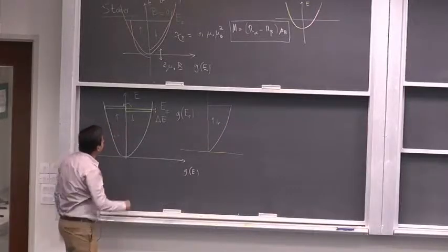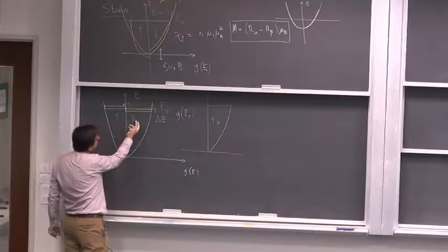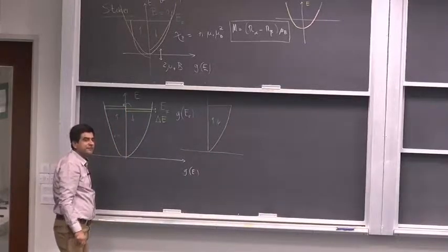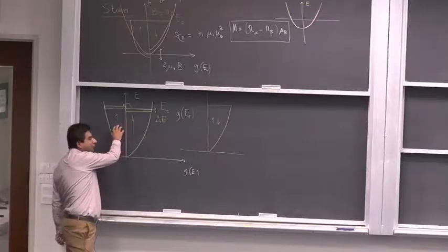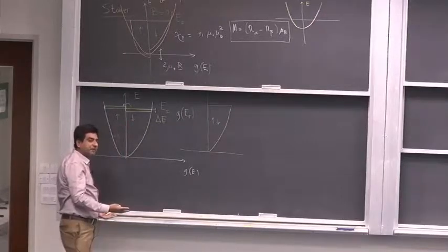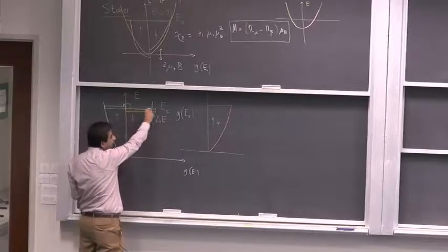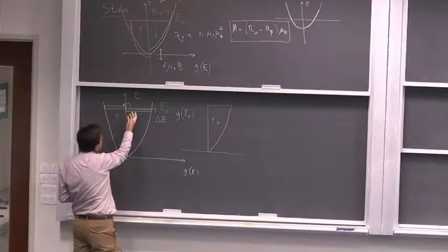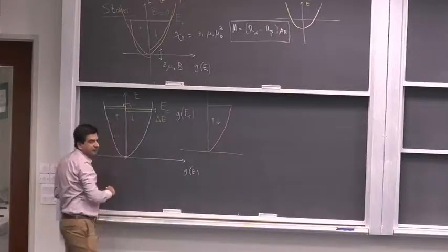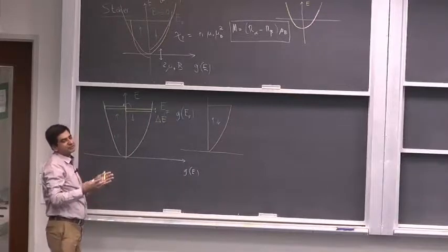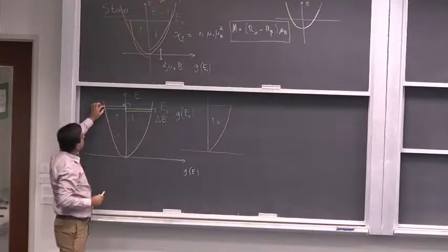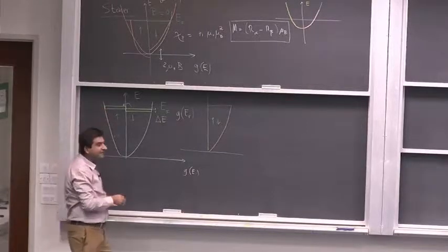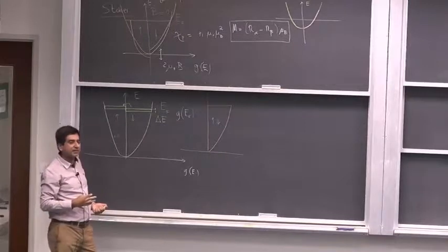Okay, so now what we're doing is we're flipping, reversing these spins and increasing their energy. Their spins must flip in order to go into this band. So we are flipping the spins of these electrons that are at the Fermi level, and since nearby levels are available, this kind of interaction can take place. So the energy of the system is going up. You see, higher energies are being populated. So the increase in the kinetic energy of the system can be determined.